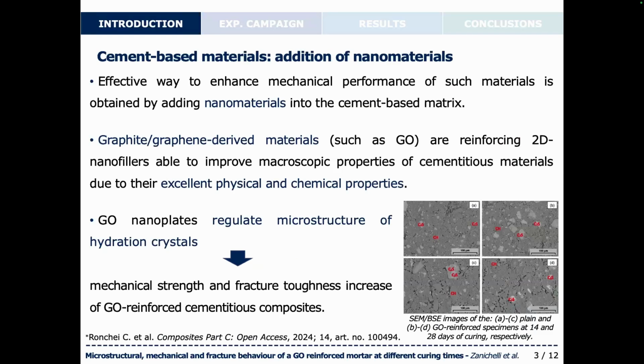An effective way to enhance the mechanical performance of such materials is obtained by adding nanomaterials into the cement-based matrix. And among nanomaterials, graphite or graphene-derived materials, such as GO, represent reinforcing bidimensional nanofillers in the form of nanoplates, which are able to improve the microscopic properties of cementitious materials due to their excellent physical and chemical properties. As a matter of fact, according to the technical literature, GO nanoplates can regulate the microstructure of the hydration crystals during the cement hydration phase, and so lead to an increase in the mechanical strength and in the fracture toughness of GO-reinforced cementitious composites.